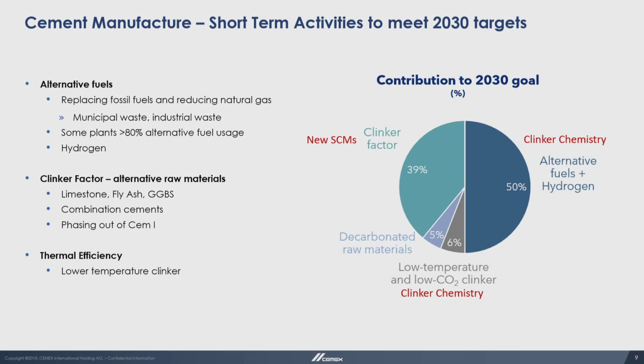So increasingly what we see is that the materials that we've relied on to give us lower CO2 are becoming more difficult to obtain. So certainly in the longer term, we'll have to look at alternative materials. In the short term, they're still here, and what we are seeing is increasing use of combination cements, multiple blending of cements, so using fly ash and slag together, perhaps in combination with limestone, and a general phasing out of CEM 1, which is the highest CO2 cement that's produced at the moment.